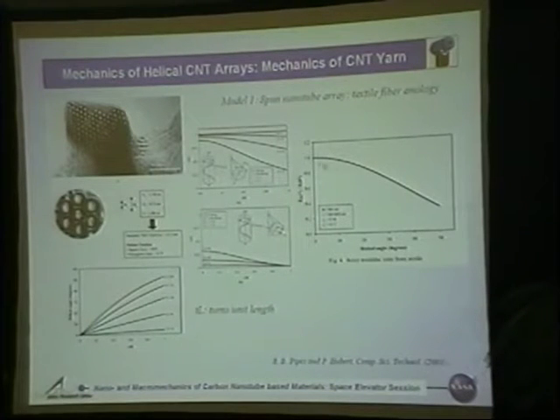Directly, let's go there. So this particular graph shows the ratio of the modulus of the twisted fiber versus the original straight single wall thing, how much it is degrading in the property. And as a function of that helical angle, and the helical angle is that twist angle. So even when you are going by 10 degrees, 20 degrees, 30, 40 degrees, this thing has degraded by almost 40-50%. You started from 1, and for 60% you have degraded.